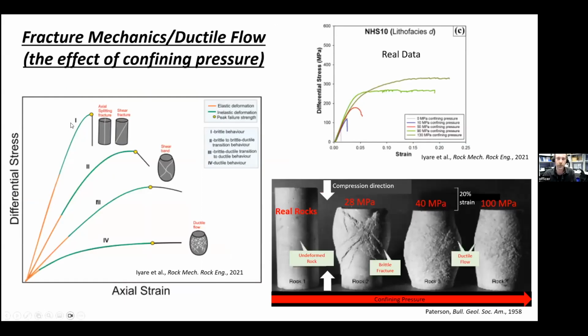So here is brittle behavior at the top. You increase the differential stress until it just fractures. But then as you increase pressure, you start to get shear bands forming and more ductile flow. So eventually you transition from brittle behavior to ductile behavior. So here's some real data in the top right here.